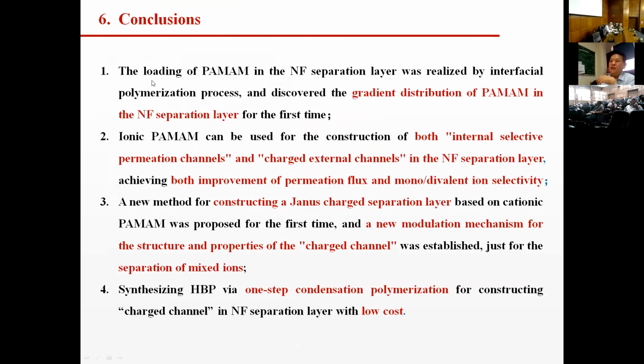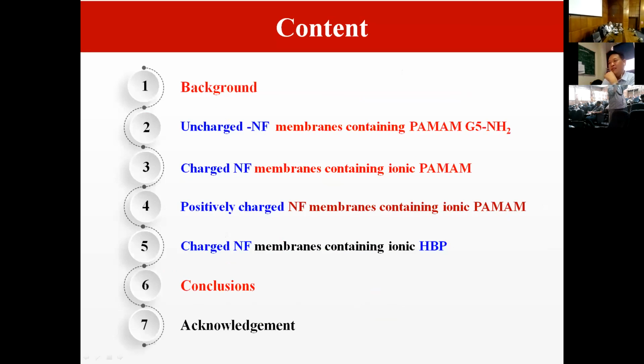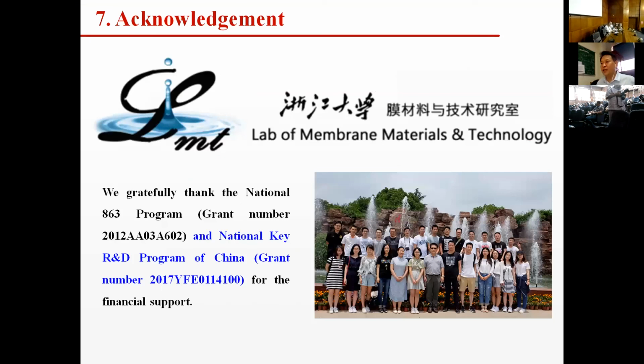So, briefly, from the discussion above, we can conclude that the research on the amino-based dendrimer, dendrimer-based nanofiltration membrane, is a new route for charged membranes. To overcome the higher expense of PAMAM, we can use a hyperbranched polymer in practical application to prepare applicable nanofiltration membranes, because the hyperbranched polymer could be prepared via a one-step polymerization process. So this is our work about nanofiltration membranes based on the hyperbranched and PAMAM polymer nanoparticles.